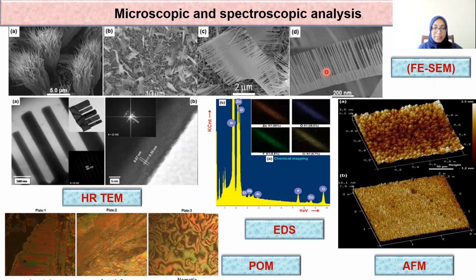Microscopic and spectroscopic analysis. The shape and size of the zinc oxide nanomaterial was examined through field emission scanning electron microscopy at various magnifications, as you can see in these images. The low resolution images, as you can see here in figure A, indicate that the zinc oxide nanomaterial has a flower shape morphology, and they are densely grown over the entire substrate surface.